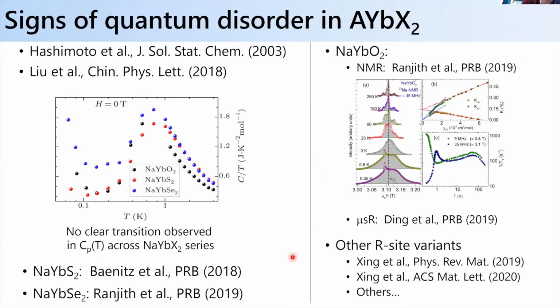Good. And so I just want to say, one of the interesting things about this system in terms of quantum spin liquid behavior is that these signs of quantum disorder are kind of ubiquitous across this alkali metal ytterbium X2 series, as long as it's in the triangular lattice structure. So for instance, if you look at sodium ytterbium sulfide, sodium ytterbium selenide, they all seem to have similar types of phase diagrams, with the energy scales just being pushed lower because the crystal field comes down and exchange parameters come down as well.